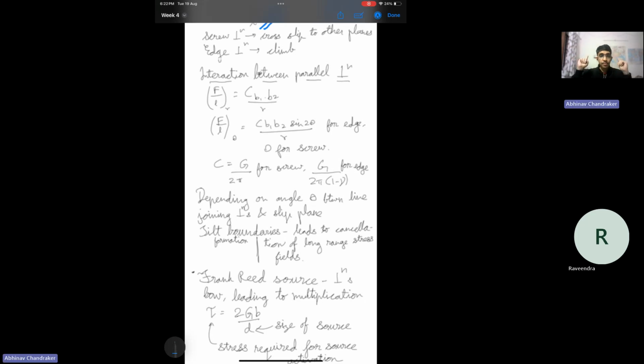Then another distinguishing aspect of screw and edge dislocations is that a screw dislocation, due to its intrinsic geometry, can cross slip to other planes. So if its dislocation line is moving in a particular plane, it has the option to shift to a different plane and continue to glide on that new plane without changing its Burgers vector. A dislocation's Burgers vector can never be changed. It will remain the same for a particular dislocation. But a screw dislocation can move to a different plane with the same Burgers vector, while an edge cannot do that.